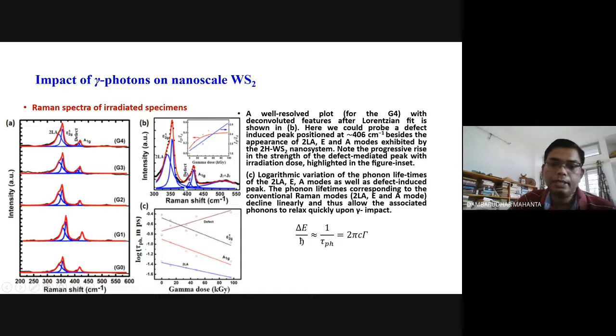for different irradiated samples, and accordingly we have calculated the phonon lifetime considering the uncertainty relation delta E is h bar, which is equal to 1 by tau ph equal to 2 pi c gamma. Gamma is the full width. So for different phonons like A1G, then E2G1 and 2LA and defect, in logarithmic scale, semi-log scale with gamma dose, we have plotted for all the samples, and we found that except defect, in all the cases it is going down.